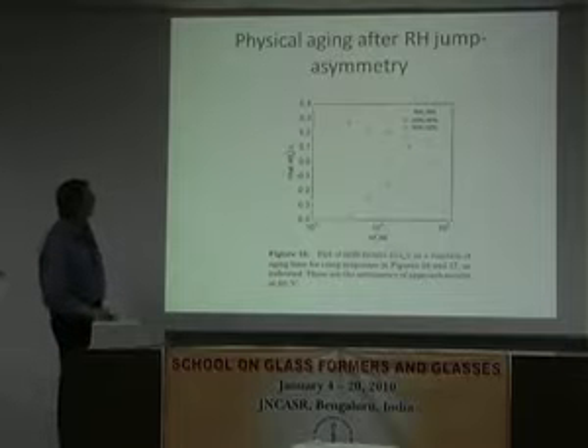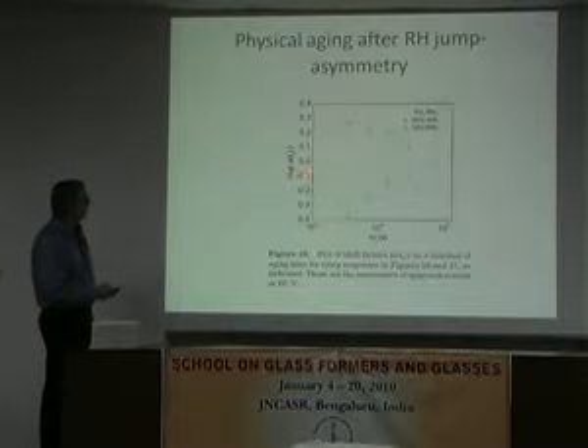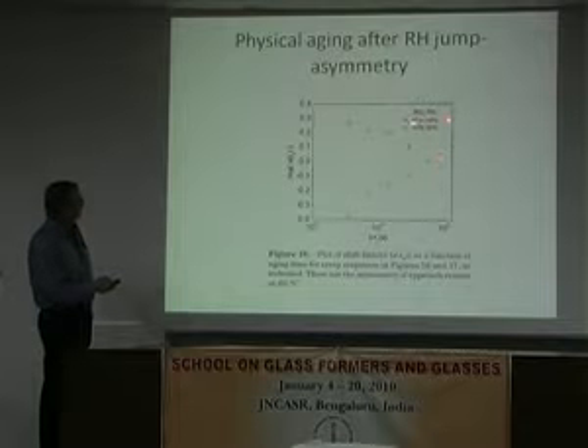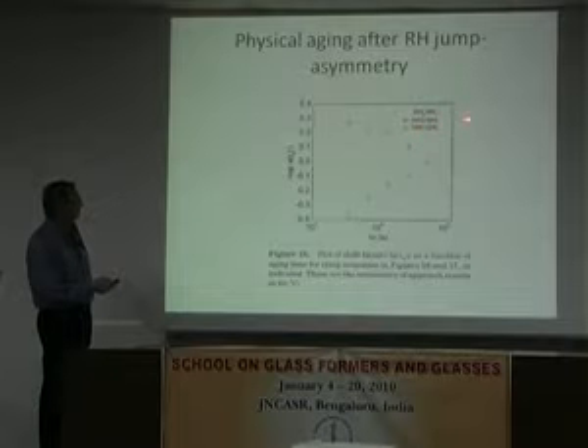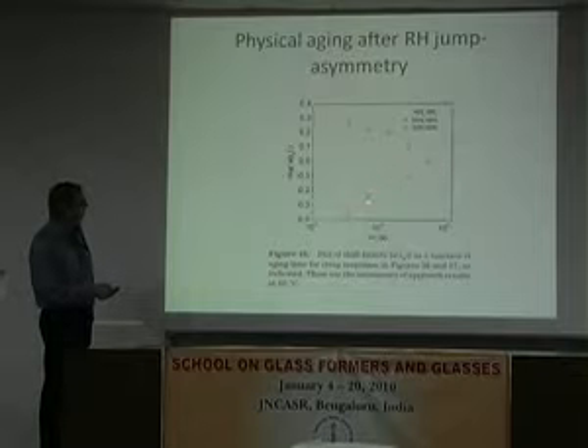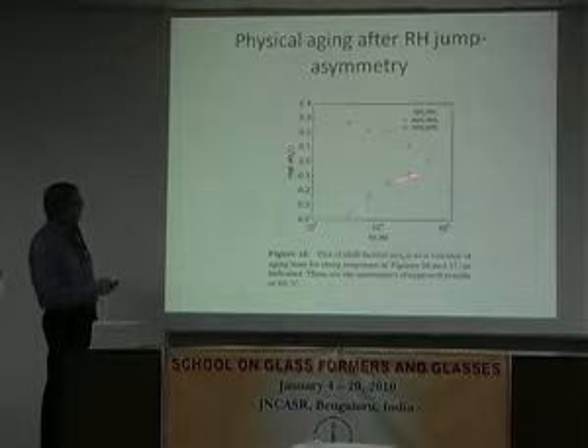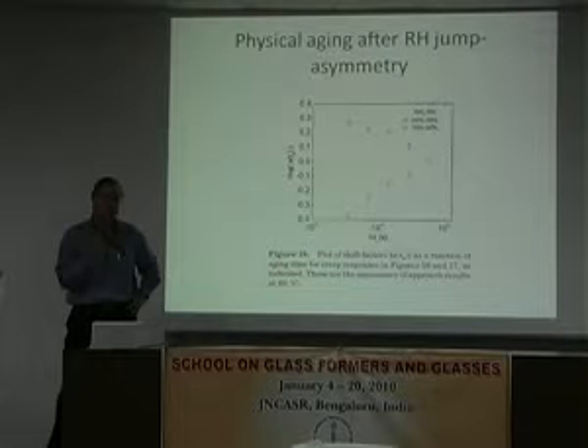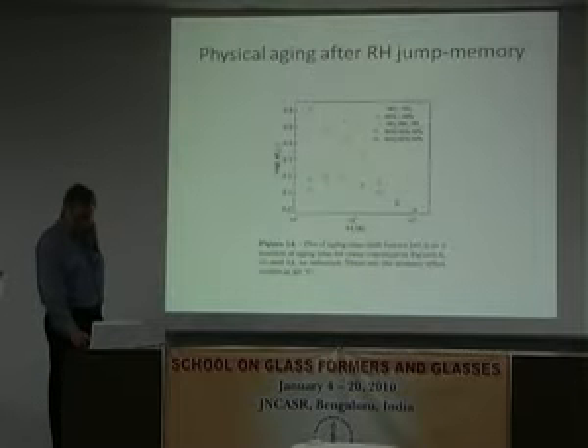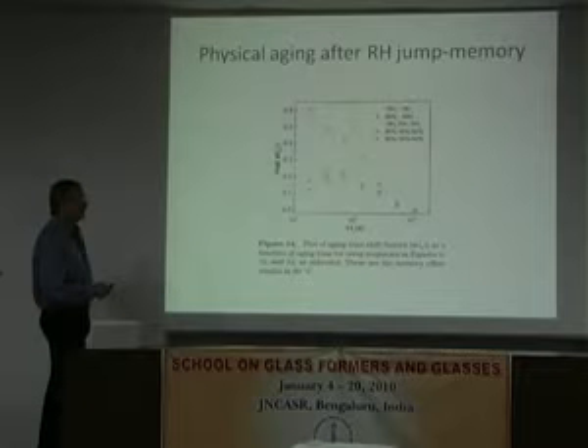And we show that we get an asymmetry of approach for the 2 to 15% relative humidity jumps up and down. So we get somewhat of an asymmetry. It's not as asymmetric as what we got in the temperature jumps. We saw that before. And we get the memory effect in the mechanical response as well.